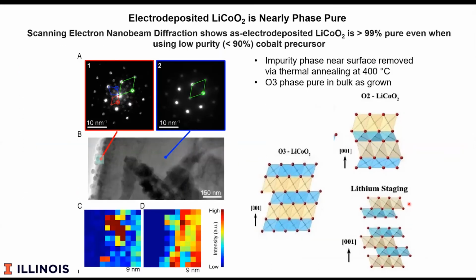Okay, so let's now zoom in, in a literal and figurative sense, and try to understand what's going on. This is work that we did with Jim Schwo and his group here at Illinois, using Jim's technique of scanning electron nanobeam diffraction, scanning over the system and looking at the crystallographic morphology. We saw that the interior of the structure was indeed O3. This is what we had wanted. But on the surface, there were impurity phases. There was a mixture of O2 and O'3 as well as some other phases.